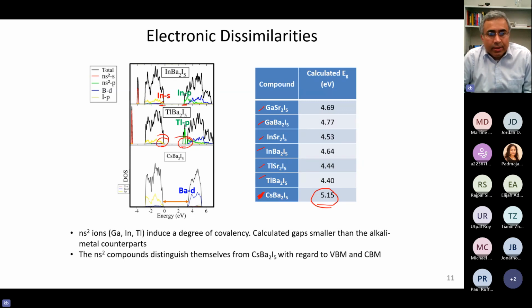And you can compare that with cesium barium iodide. You see there are differences in the electronic structure and also in the band gap. Now let's see what happens with that. So instead, in case of cesium barium iodide, you dope with europium. Europium would create an F state right there, and then europium D and barium D would be right there, and then emission will happen between those two. We don't have such a situation in our new Ns2 compounds. So what will happen there?